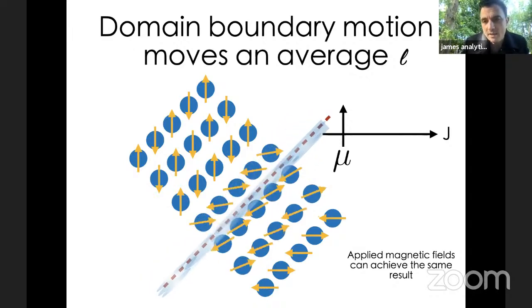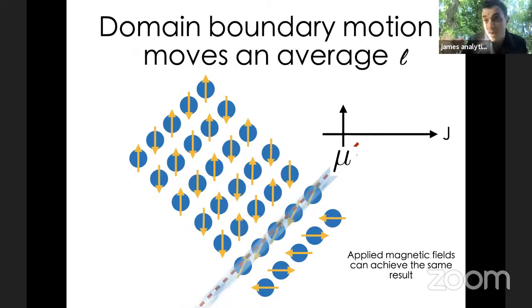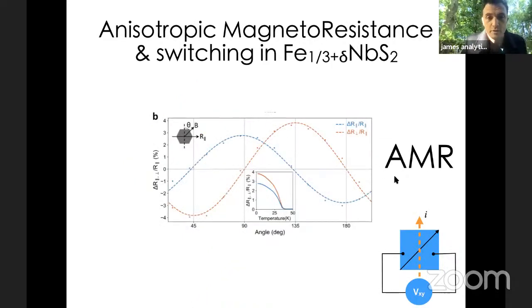And so by applying a magnetic field, you can actually also shift those domain boundaries in an antiferromagnet. And then you can also change the angle of the magnetic field in the system, and then see how that compares with your switching of your electric field. So here's the angle dependence of rotating that magnetic field in the plane of the sample, and here's the resistance that you get. The blue resistance is the changes to the longitudinal resistivity. The red resistance is the changes to the perpendicular resistivity.